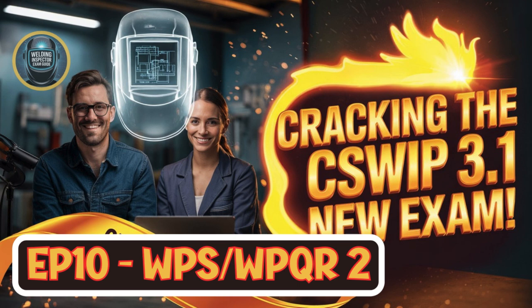Now, the actual heat input, we need the K factor. Right. For MAG welding, we said K is 0.8. So it's 1.2 kJ/mm times 0.8. Which gives us 0.96 kJ/mm. 0.96. That tiny number dictates so much about whether that weld will perform safely. It's incredible. It really is. It highlights the level of control and understanding required in modern welding.